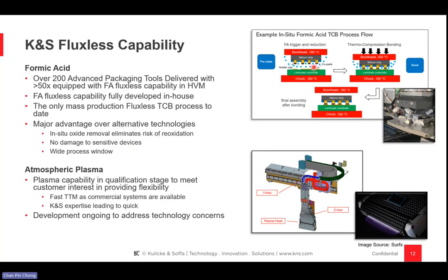So this is in situ, that means as a bond, it basically introduces formic acid. So you're actually cleaning and bonding at the same time to reduce the risk of reoxidation especially on the copper surface, right? And of course, there's no damage to the sensitive device. It's a chemical process, so it cleans. Formic acid has been around in the industry for many, many years. It's a known process of clean, and basically we are introducing this as an in situ formic acid TCB flow. So it creates a wide process window, as we can see that quite a lot of equipments are in high volume manufacturing production. So we have done it over the last couple of years working with different customers, and this is basically a proven technology in production.